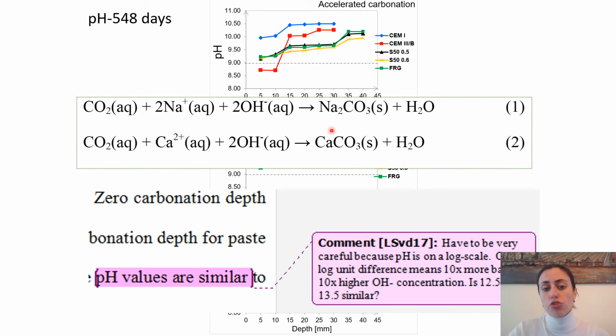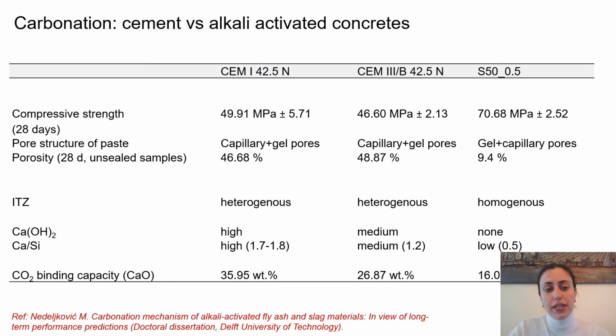We also should note that on these graphs, the pH is presented on a logarithmic scale. So there is a huge difference between 9 and 10, or 12.5 and 13.5, like is pointed out here, because that means 10 times higher OH minus concentration.